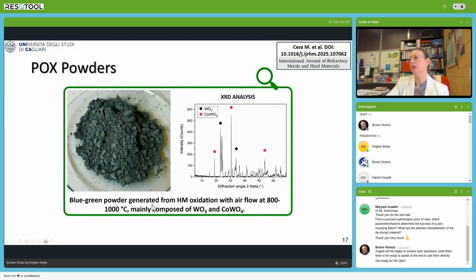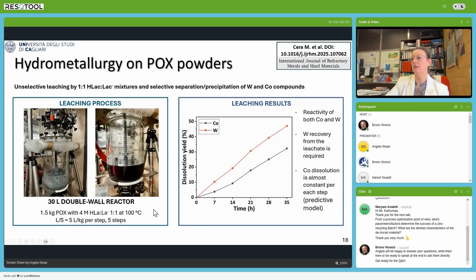So in this mixture, cobalt has a lower reactivity towards organic acids with respect to the reduced powder. Instead, tungsten is more prone to react with organic acids. In these cases, we have made a variety of experiments, and we found that by using lactic acid solution in buffer conditions at 4 molar concentration, it is possible to dissolve, as you can see in this graph on the right side, both cobalt and tungsten. Also, we can proceed by steps, using renewed solutions for dissolving increasing amounts of cobalt and tungsten.